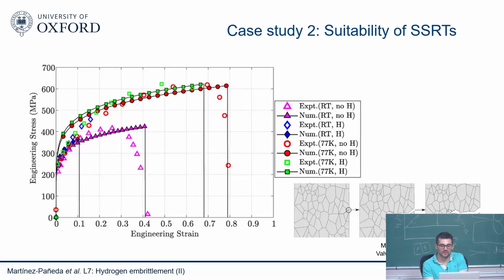So what they did in nickel, they said, okay, we're going to run experiments at room temperature with and without hydrogen, and we're going to do experiments at very low cryogenic temperature, 77 K, with and without hydrogen. And then we're going to look at the fracture surface and see whether we see embrittlement or not. The reason for doing experiments at very low temperatures is that in those cases, there's no hydrogen diffusion and there's no hydrogen plasticity interactions. So the only thing that you have is hydrogen trapped in grain boundaries. So is the hydrogen in the grain boundaries enough to trigger decohesion, or do we need extra mechanisms?